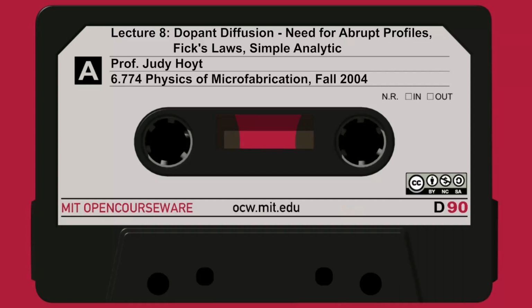There's a flux coming in from the left face, and a flux going out the right face. Just by bookkeeping, we can write a simple equation that says the change in concentration, delta C, in the time period, delta t, is equal to the difference in these two fluxes, the incoming flux minus the outgoing flux, divided by the distance, delta x.